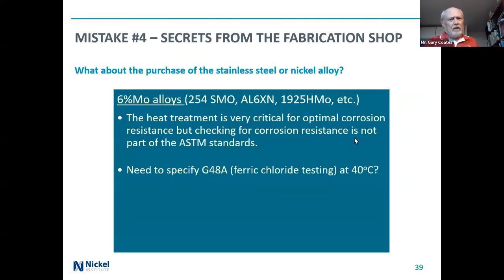For the 6-moly alloys, the heat treatment is critical. The heat treatment temperatures in ASTM are at the minimum, and for some of them, if you use just the minimum, they will not actually give good quality results. So it is, I would say, important to check for corrosion resistance. And there, for example, the ASTM G48A ferric chloride test at 40 degrees C is a good idea to have.